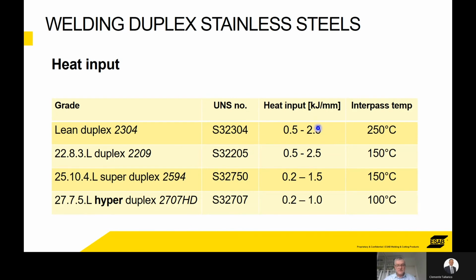In terms of heat input, there are very strict recommendations on every grade. For instance, a standard duplex, we're talking a maximum of 2.5 kilojoules per millimetre with an interpass of 150. The hyperduplex, which is obviously more highly alloyed, we're talking a maximum of 1 with an interpass of 100. And basically, why do we do that?